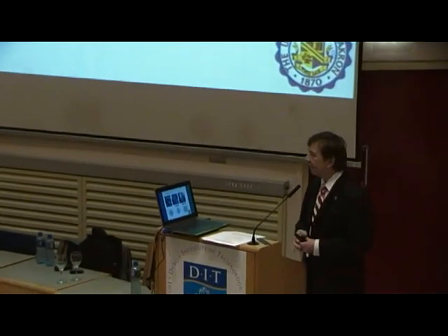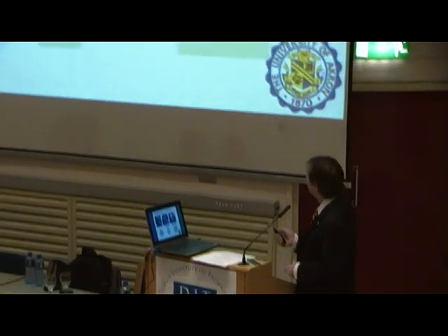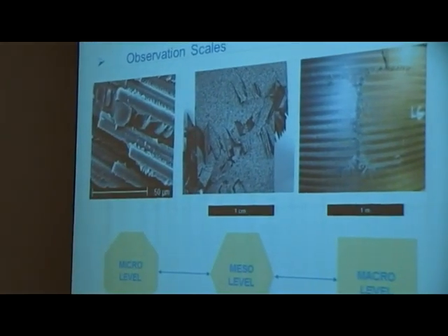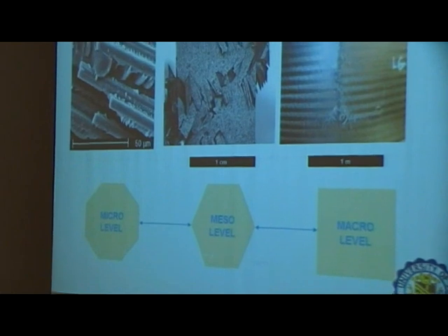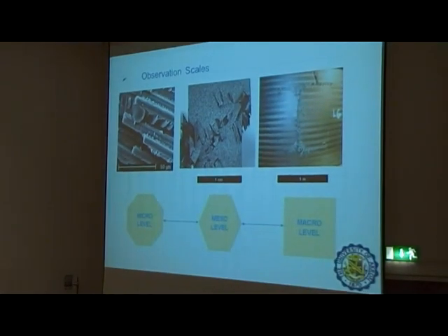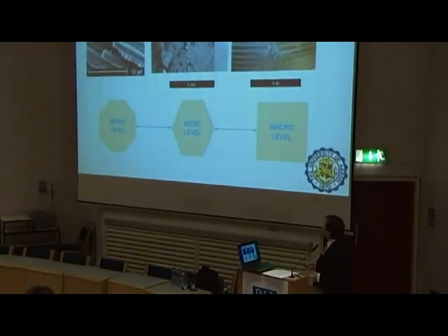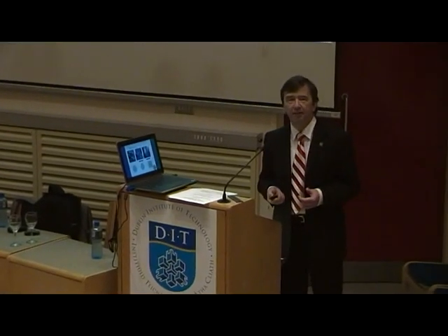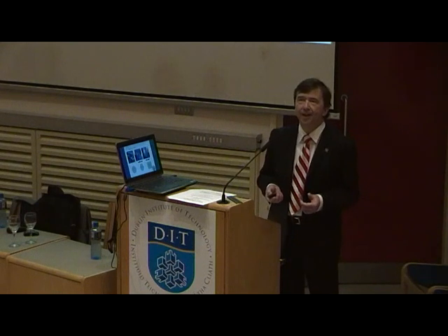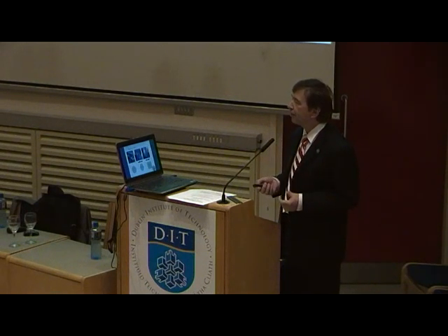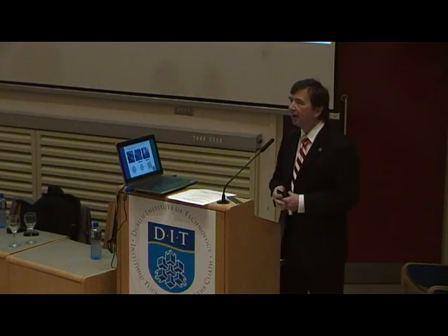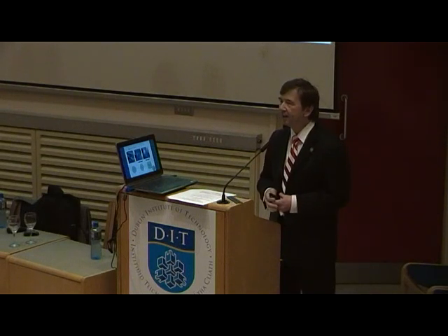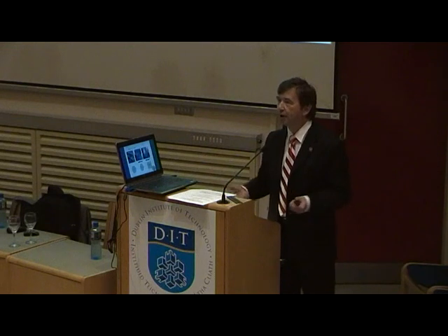Of course, when we test, you can see that at different levels, we will focus on different modes of failure. We can see at the micromechanical level the adhesive or cohesive fracture of the material itself. We can see from the sample level the tension results, which look like shear, and from the structural level, we can see the damage due to application of the internal pressure, which makes the crack driven by the geometry of the cylindrical structure itself.